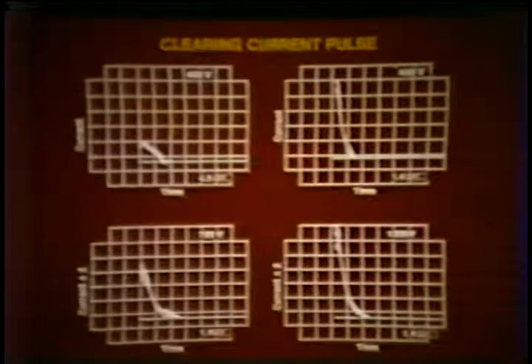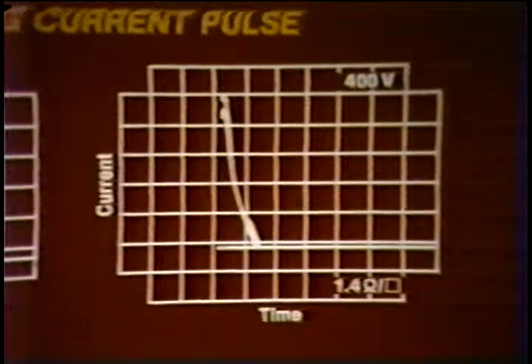To operate the circuit, we first close switch A, which charges up the 1 microfarad capacitor to a voltage V. We then open switch A and quickly close switch B. The full voltage is then instantaneously applied on the model capacitor, causing a clearing event and a current pulse in the current transformer. This pulse can be recorded on a storage oscilloscope and is shown here. We see a comparison of the current pulses arising from the clearing events for metallized film with different resistivities and different applied voltages. Integrating the area under this current trace, we can calculate the clearing energy. We see that the thinner, higher ohms per square electrodes require much less energy to clear than the thicker 1.4 ohms per square electrodes.